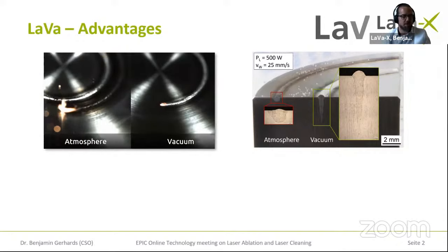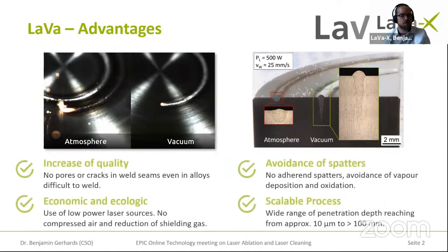So we have several advantages for our process in contrast to welding at atmosphere. For example, we have the increase of quality. We have no cracks or pores. And this also applies for alloys or materials that are difficult to weld. We have the avoidance of spatters. If spatters occur, they are not adherent to the surface. We do not have any vapor deposition on the material surface or oxidization.